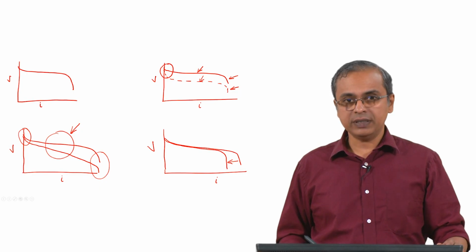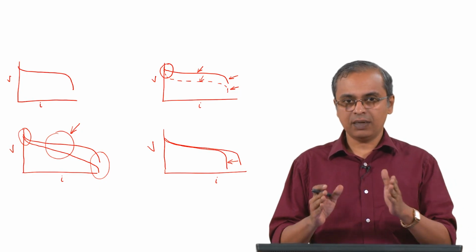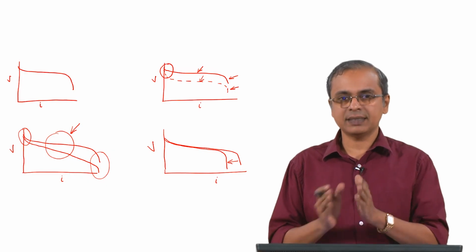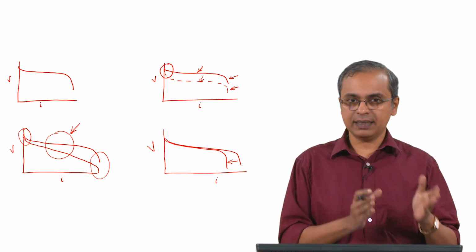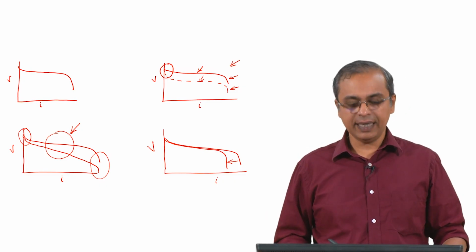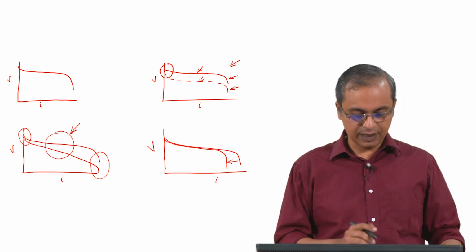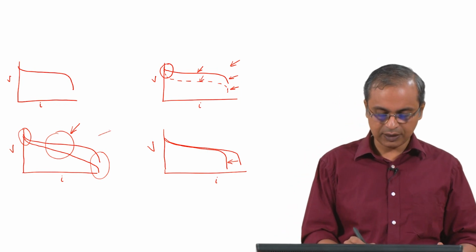So, we now see that using just the polarization curve, you can have three situations. In one case the reaction site has become bad, and that would be this example here. The other case would be one where the membrane conductivity or the electrolyte conductivity has become bad, and that would be this situation out here.